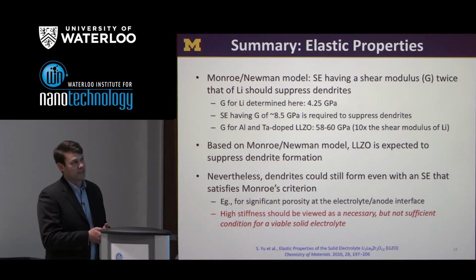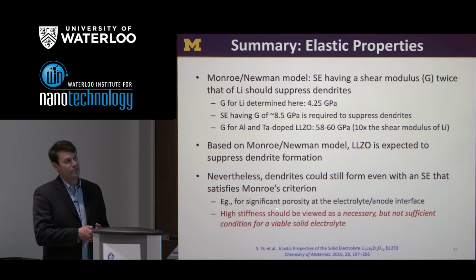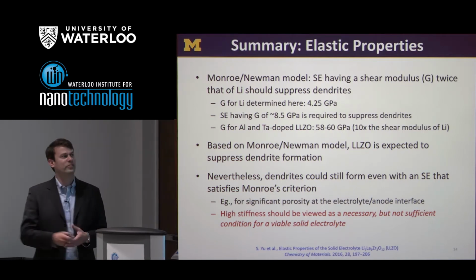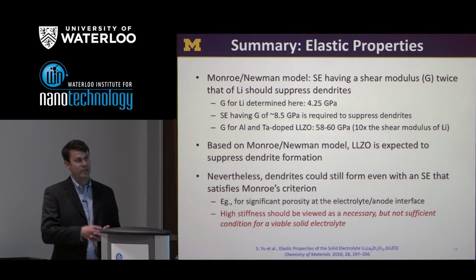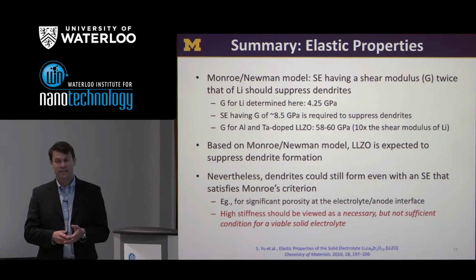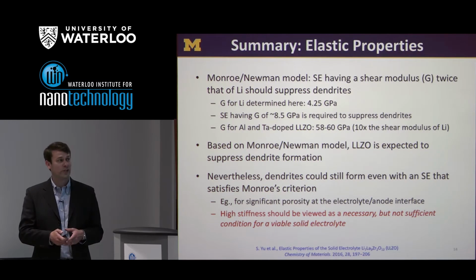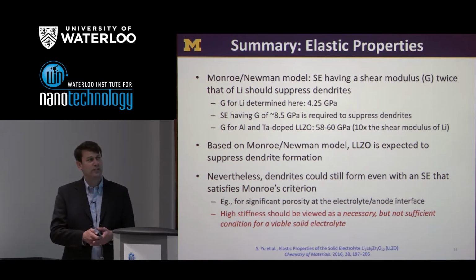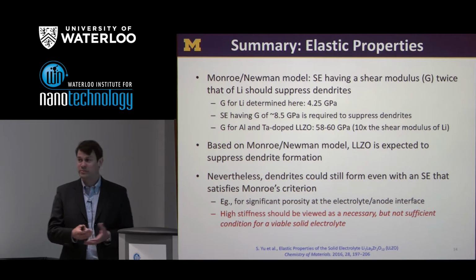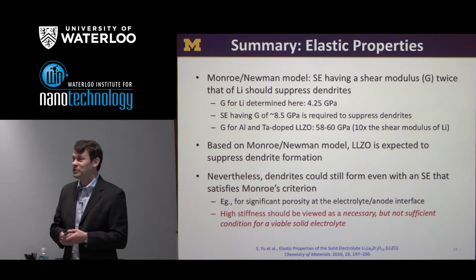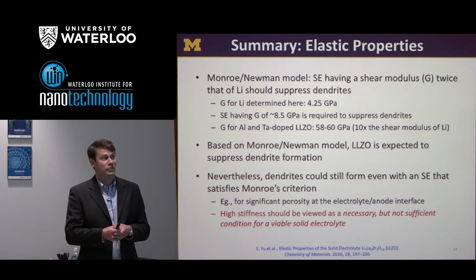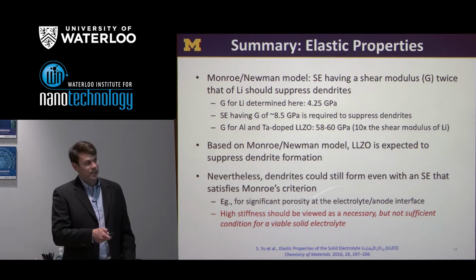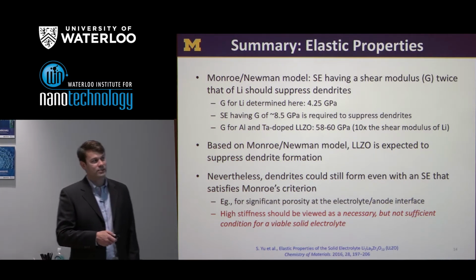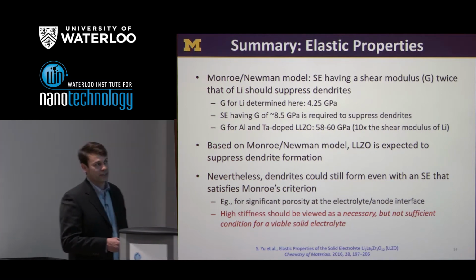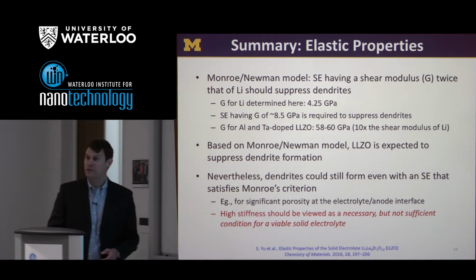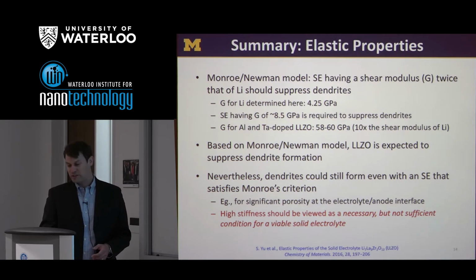We should, however, be careful. Not every solid will have, say, the low porosity that we've seen in this particular sample, and assembling that solid electrolyte into a cell and maintaining, say, low porosity at the electrode-electrolyte interface is something that may not be easy to do. So even though we have a bulk system that looks like it's suitable, putting that material into practice could cause some problems or raise some issues. So I like to say that high stiffness is a necessary but not sufficient condition for a viable solid electrolyte. In fact, that's the whole point of the talk, that there are some other issues that we also need to address beyond just this dendrite suppression.